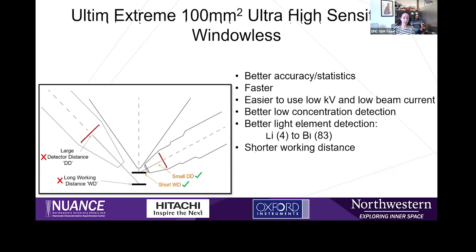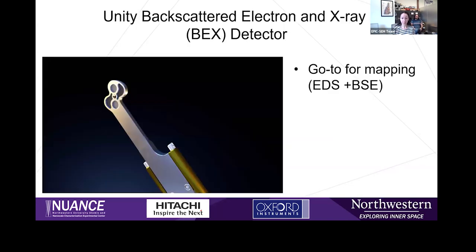The electron trap that is part of this detector, while it's really great for allowing this low kV and light element analysis, does make things less accurate if you're working at accelerating voltages above 7 kV. So you'll still want to use the Ultimax if you're doing higher kV work.